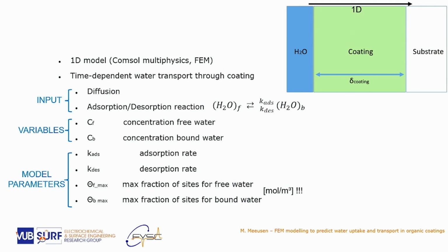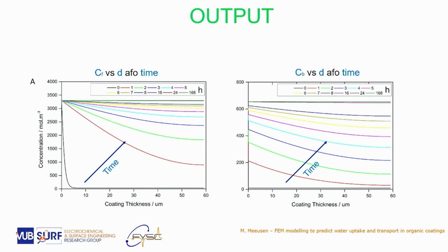So one of the models which relates to the coating is, as we are measuring these transport properties with impedance measurements, we are trying to come up with a model that predicts the transport of the electrolyte through the coating based on input data, which are gravimetry, infrared measurements, for example, and DSC measurements. So this is to predict this type of parameters. These parameters are then solved in the finite element model, which allows us to predict the free water and the bonded water as a function of time. And out of that, we try to do a validation.